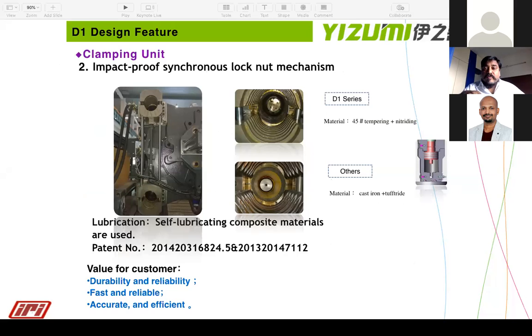Okay, so what is a unique design feature about the Yizumi is that we have some patented technologies in the two platen machines. Particularly, a very important mechanism in a two platen machine is the lock nut. You can see the left side of the lock nut. It is very important that all 4 lock nuts close at the same time, and also that they do not give a loud sound. It should not impact very high on the nut. If we have a high impact strength on the nut, then the life will come down, and you also get heavy noise. So we have a patented toggle design here. You can see a lever design on the left side. That will make sure that the lock nut closes perfectly at the pin.